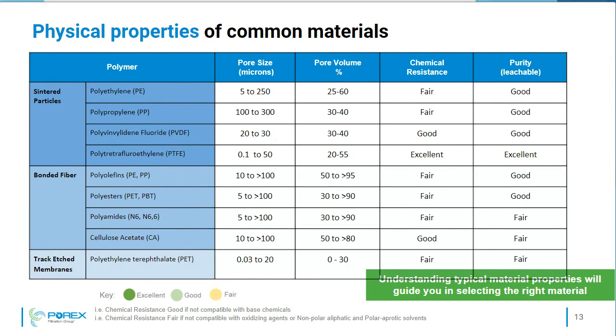When you look at, say, the sintered material options, we describe this material type as a well-defined complex 3D geometry that makes a porous hydrophobic material suitable, for example, in venting or waterproofing, for sealing or keeping fluids outside of the device. The bonded fiber range, we typically see in applications for wicking or in that sample intake step that's designed to control the liquid and volume speed. So you might reference that as a conjugate pad, for example.